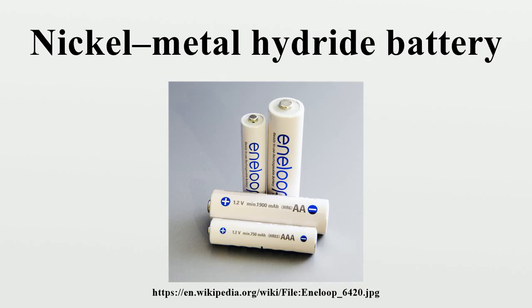The self-discharge is 5-20% on the first day and stabilizes around 0.5-4% per day at room temperature, but at 45 degrees Celsius it is approximately 3 times as high. Low self-discharge: the low self-discharge nickel-metal hydride battery has a significantly lower rate of self-discharge. The innovation was introduced in 2005 by Sanyo, under their Eneloop brand.